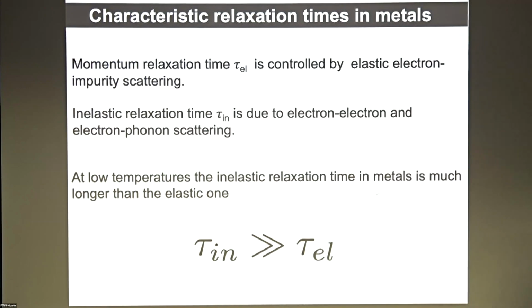And there are several inelastic relaxation times. But what if you take a frequency-dependent relaxation time and associate the frequency-dependent part with tau elastic and the independent part with tau inelastic? That is, if you try to extract the frequency-dependent relaxation time from the data. From which data? From the scattering data, from optical conductivity data?